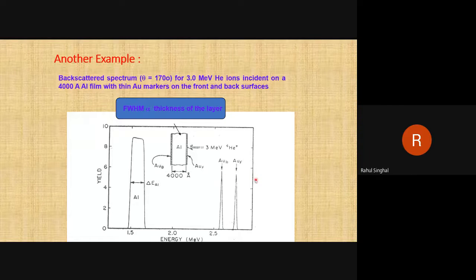Obviously gold will come at higher energy because the mass of gold is much higher than aluminum. We have a very thin layer of gold, so we have a very thin peak of gold coming from the surface, and gold coming from the bottom. For the aluminum, the width is too large. It's 4000 angstrom, so the peak width is also very high. Why? Because once the 3 MeV helium comes here, it will hit an aluminum atom from the top, then from the inner layer, then from the next inner layer. As soon as they come back, their energy goes down. It keeps decreasing: the deeper the heliums go, the lesser their energy after the backscattering. So once you get the peak, it will go down, and then suddenly it will come back. So the width of this peak is directly proportional to the thickness of the layer.